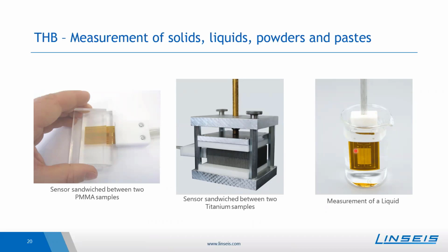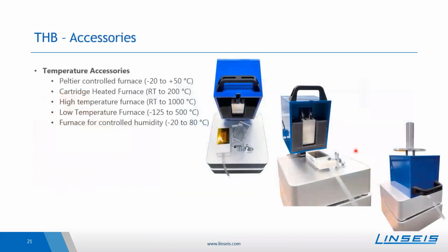To realize different applications, there's, of course, a broad range of accessories. So on the one hand, there are different furnaces available for different temperature ranges. So here in the pictures, you can see our Peltier cooled furnace, which can measure from -20 to +50 degrees Celsius. So especially suited for polymers. Here you have then a sample holder, where you just prepare the sensor sample sandwich, and then here on the top, there's the possibility to put some weight on top so that the configuration is also pressed together.